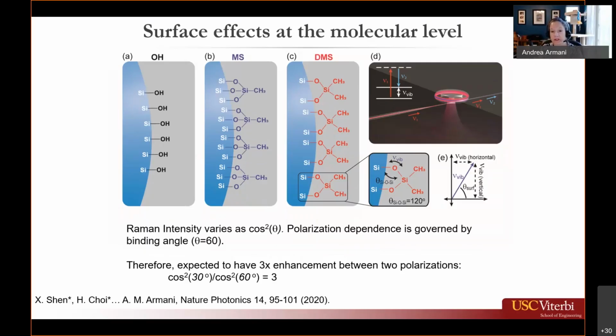An important feature of this surface chemistry is that the Si-O-Si bond has a fixed angle. The vibrational angle of this bond is 120 degrees, and Raman has a polarization dependence, and it's governed by that binding angle. So therefore, depending on which input polarization of light we used, we would expect there to be a difference in the efficiency of our Raman lasing. So we would expect about a three-times enhancement between those two polarizations. That would give us an experimental way to probe if the enhancement we're really seeing is due to that surface chemistry or due to some other factor or feature in our device.